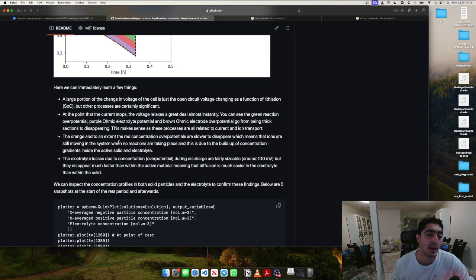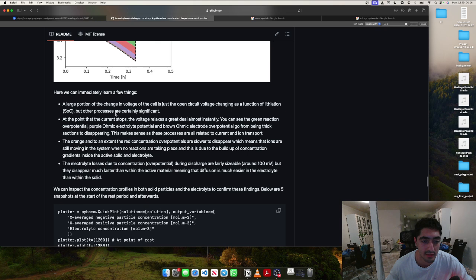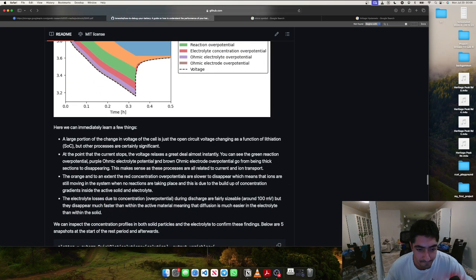Just continue. Here we can immediately learn a few things. A large portion of the change in voltage of the cell is just the open circuit voltage changing as a function of lithiation, state of charge, while other processes are certainly significant. At the point that the current stops, the voltage relaxes a great deal almost instantly. You can see the green reaction overpotential, purple ohmic electrolyte and brown ohmic electrode overpotential go from being thick sections to disappearing. This makes sense as these processes are all related to current and ion transport.